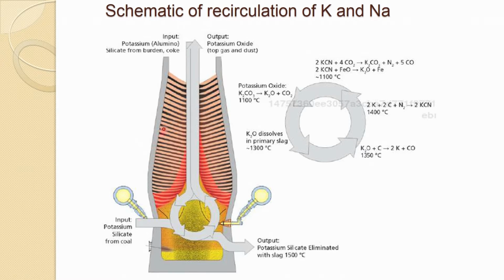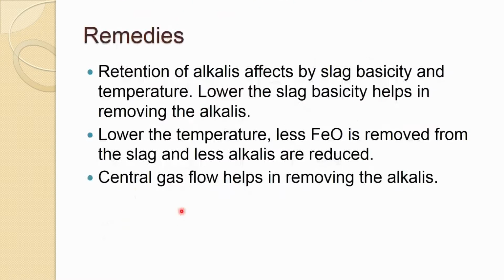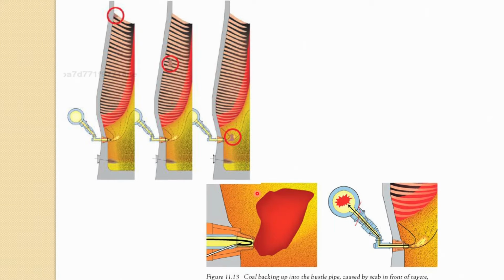Sometimes of course, this can stick to the scaffolding, and sometimes it travels down, and it travels down up to here; this schematic shows actually. So, here the buildup of those fines which is traveling down hasn't reduced much, and finally it hasn't melted and reduced that much. It has reached the tuyere region, probably in front of the tuyere, and that is a big mass chunk and it is blocking the tuyere, sending back whatever is coming from the tuyere out, and that creates a dangerous situation and some explosion may occur in the pipe. So, these things happen sometimes if this is not taken care of, and it is quite dangerous.